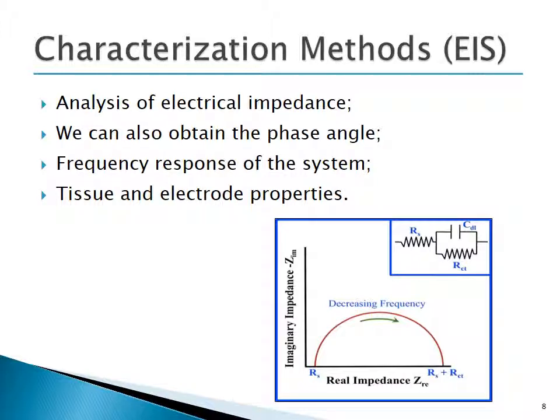In electrochemical impedance spectroscopy, we apply a known voltage or current, and we measure the corresponding electrical impedance. Basically, it gives us the frequency response of the system. If we apply a sinusoidal voltage, we can also obtain the phase angle of the system. It allows us to study both tissue and electrode response and properties, and since it is a non-destructive technique, we can use it without damaging the brain tissue.